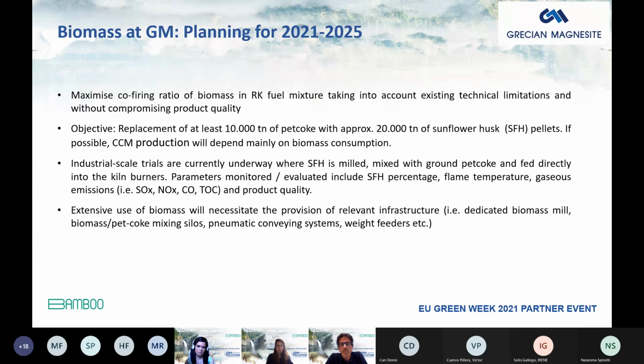Our immediate planning for 2021 and the period between 2021 and 2025 is, of course, to maximize the co-firing ratio of biomass in the rotary kiln fuel mixture, as I said, taking into account existing technical limitations without compromising product quality. The specific objective is to replace at least 10,000 tons of pet coke with approximately, as we currently see it, 20,000 tons of sunflower husk pellets.